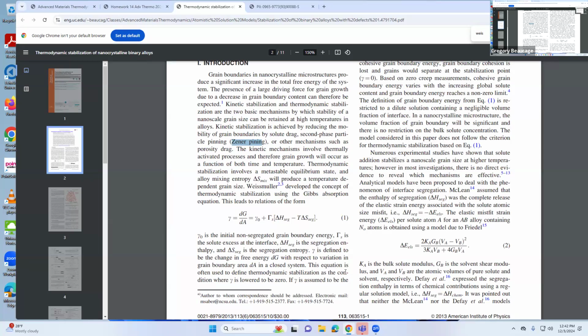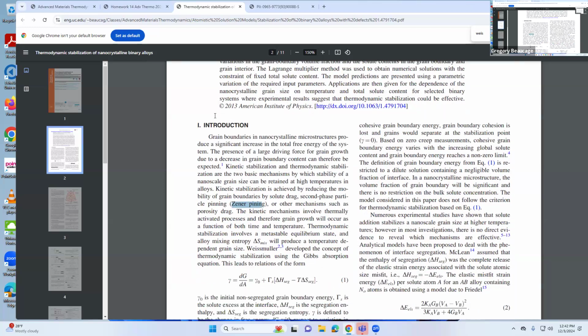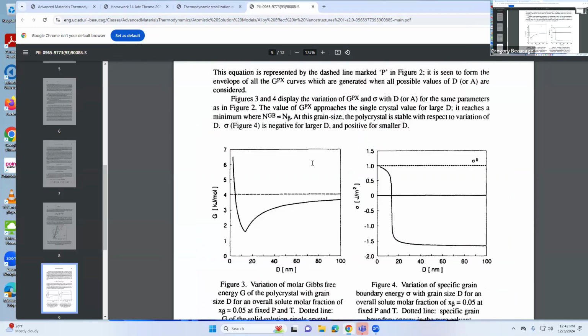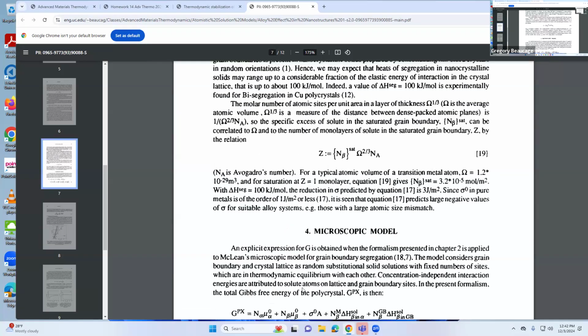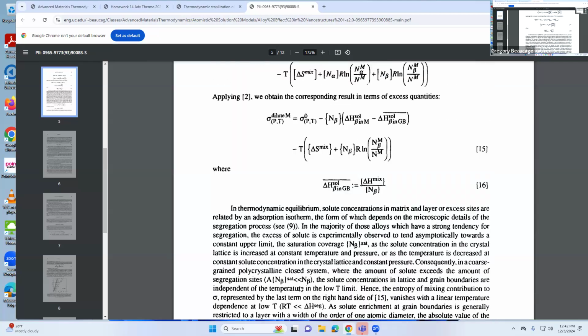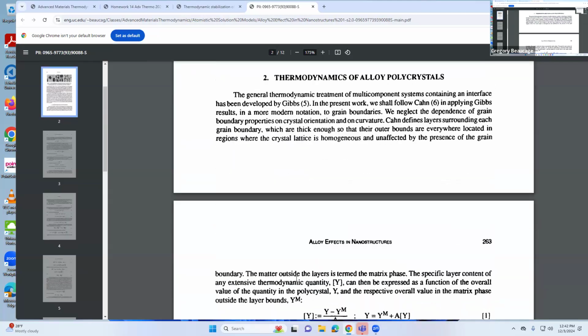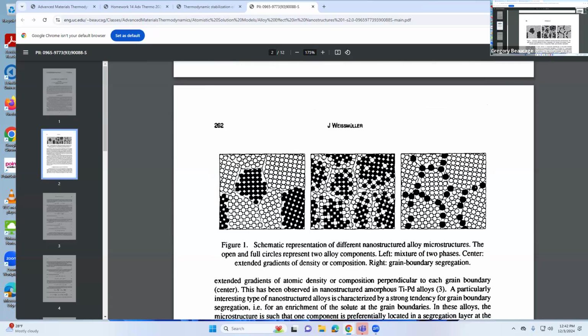So then after 93, people came along with the idea that when the particles are inside, there's a strain on the lattice, especially if you have mismatched atoms in the metal alloy. So these things are strained in here, and that actually drives the solute to the interface. That's strain. So the free energy can drive it to the interface, or this elastic strain can drive it to the interface. Right. So Weissmuller is missing that elastic strain part, and it turns out the elastic strain can be the dominant feature. In fact, in this paper, he finds out the elastic strain is the dominant feature.